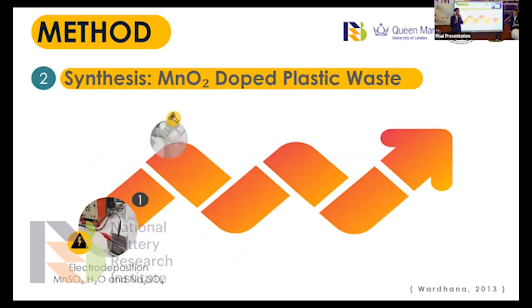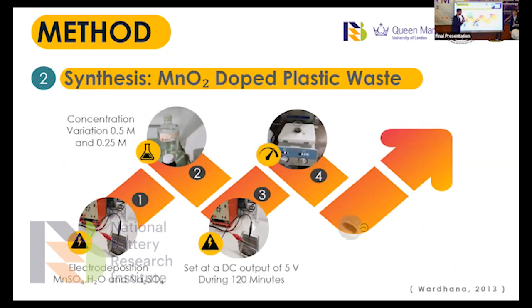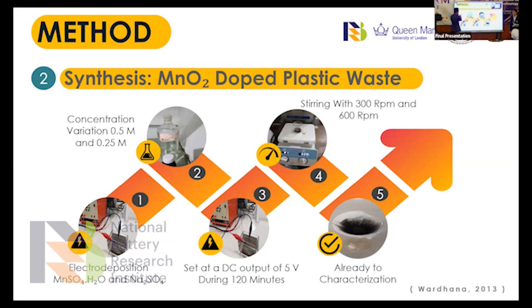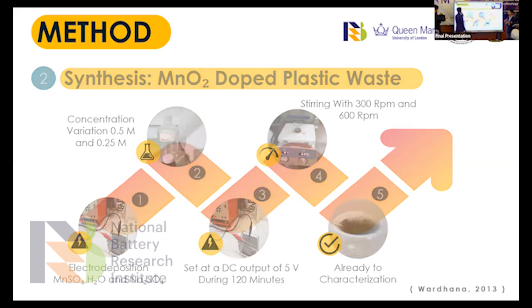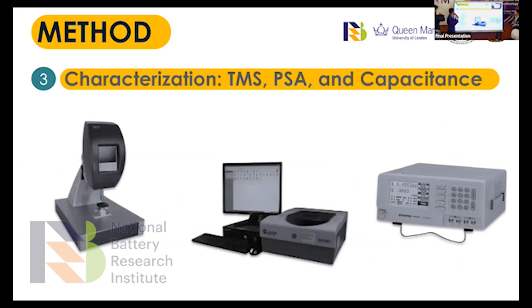The second step is electrodeposition using manganese sulfate and sodium sulfate as precursors with various concentrations, 0.5 molar and 0.25 molar. After that we stir with 300 rpm and 600 rpm. To prevent agglomeration, we use ultrasonication. For characterization, we use three methods: topography measurement system, particle size analyzer, and capacitance.